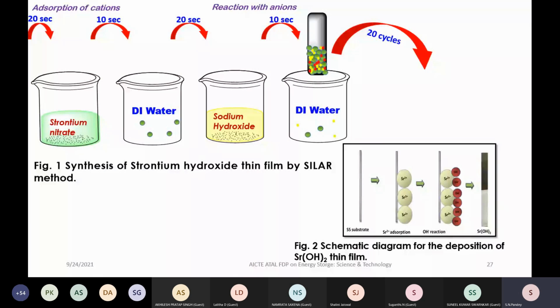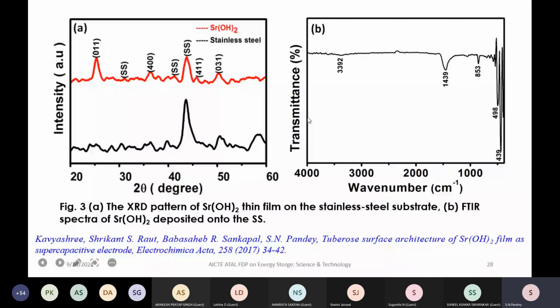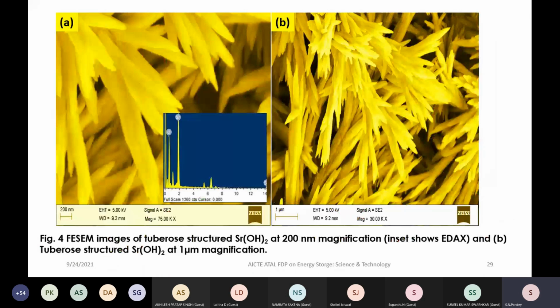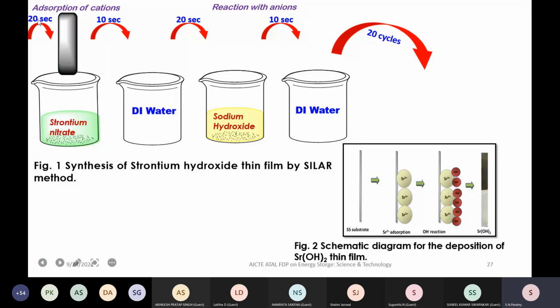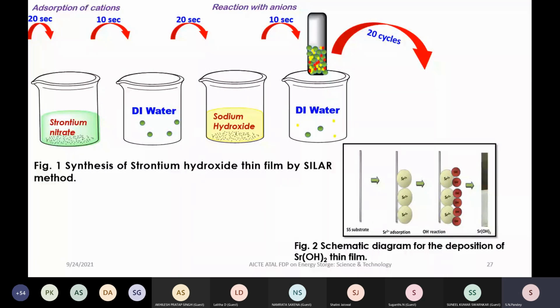So here one can see that we have to optimize it. Optimization is also very necessary. How much time you have to dip in the first one, and the second one, how much time you have to put in the DI water. So we have optimized it, and the optimization is shown here. Let us go back. Oh, sorry, I am going in the forward direction. So see that we have optimized it: it should be here for 20 seconds, then it should go to the DI water for 10 seconds, then to the sodium hydroxide for again 20 seconds, and to DI water for 10 seconds. So in this way, one cycle has been completed. So we repeated it for 20 cycles.